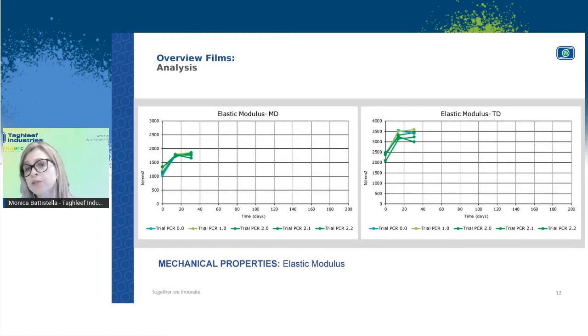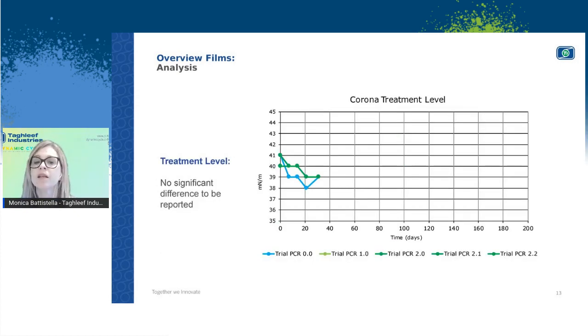And then we have the elastic modulus. You see that there's quite a fine tuning of all the samples, but they are very close to one another. The last point that we checked, which was very significant and important for us, was the treatment level. We were wondering if the mechanical recycled content could somehow impact the properties of the surface when it comes to treatment, because treatment is a very important parameter in order to be able to convert the film, so to laminate and print it.